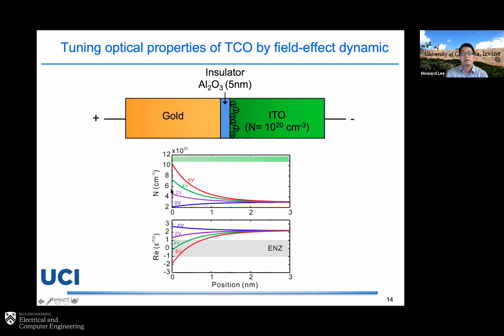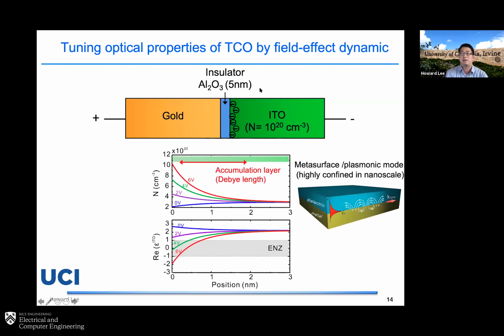You can clearly see that by applying bias, you can change the carrier concentration quite significantly. At the same time, the permittivity can change from positive to negative, or even reach this ENZ regime here. The permittivity change is quite strong. But there is a certain limitation: the length of this accumulation layer is actually quite short, only 1 or 2 nanometers. That's why, to make use of this effect, you need to integrate it into a plasmonic or metasurface structure where the field is highly confined at the interface here.